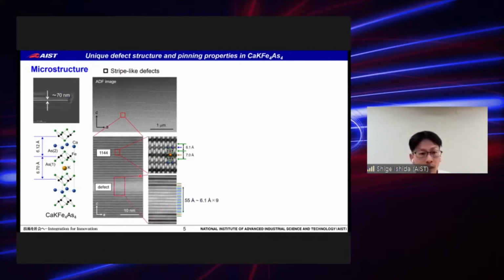Then when the bright stripe defect is magnified, we found that the zigzag structure, namely the iron arsenide layer, is maintained, while the alternation of calcium and potassium layers is violated. Here, the thickness of the defect is about 55 angstroms, which is 9 times the calcium-iron interlayer spacing sandwiching the calcium layer. So this defect likely corresponds to a 5-unit cell of calcium 122.